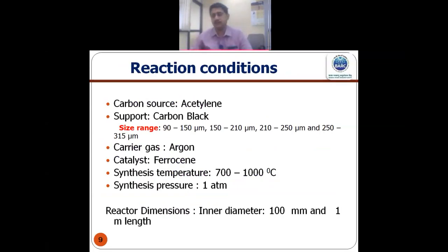Now for our process, we have chosen acetylene as the carbon source, which is very readily available and cheap. A support material called carbon black. I'll tell why carbon black has been chosen. Then a carrier gas argon, catalyst ferrocene, which on decomposition gives iron nanoparticles. Synthesis temperature we have kept from 700 to 1000 degrees centigrade, and we have used atmospheric pressure. Now our objective is to make it in an economic way. So we have chosen all the raw materials which are cheap.